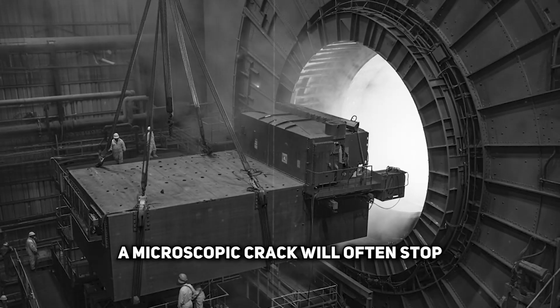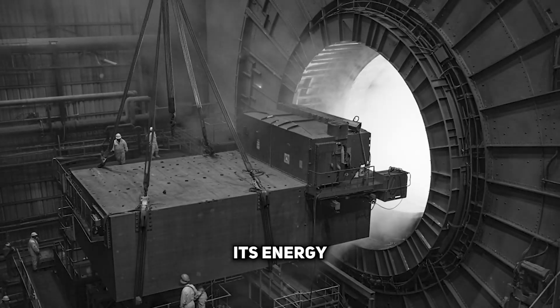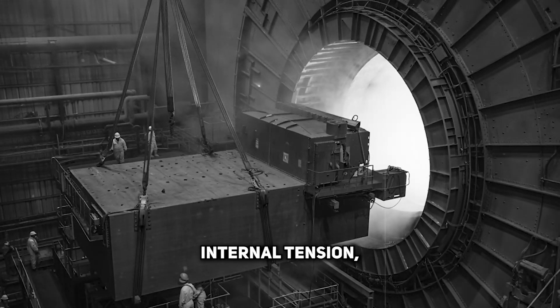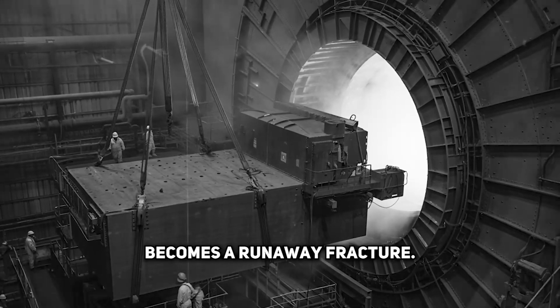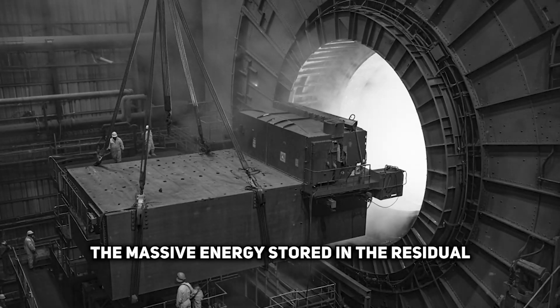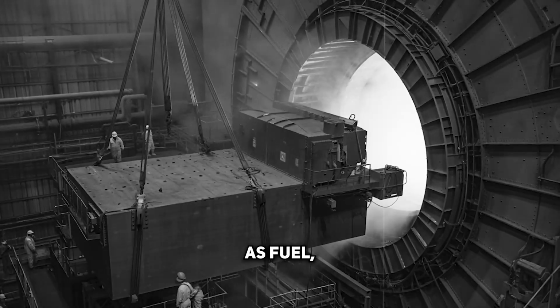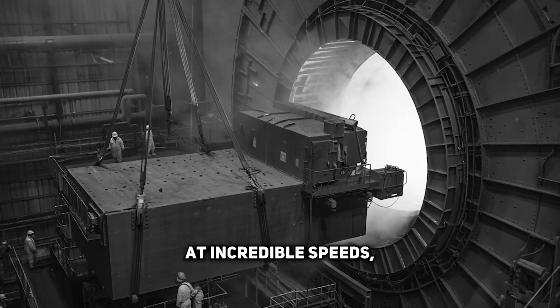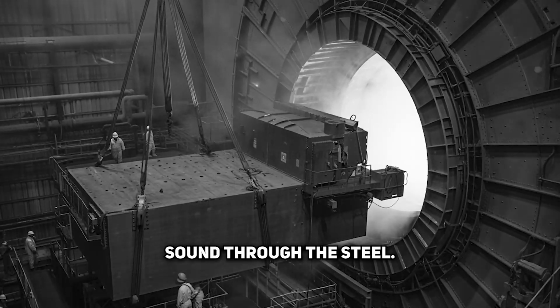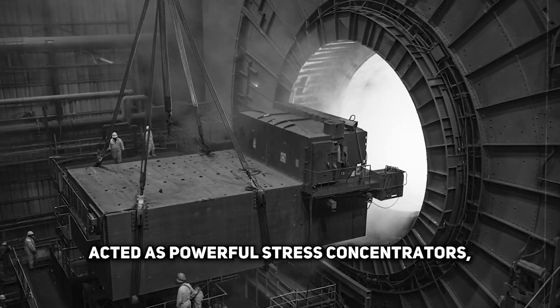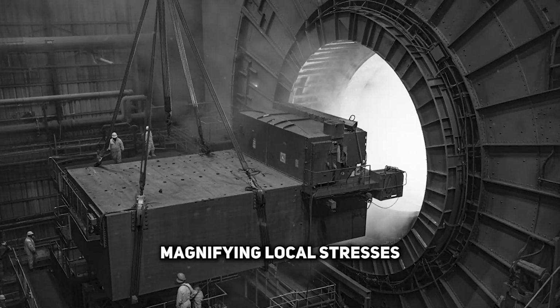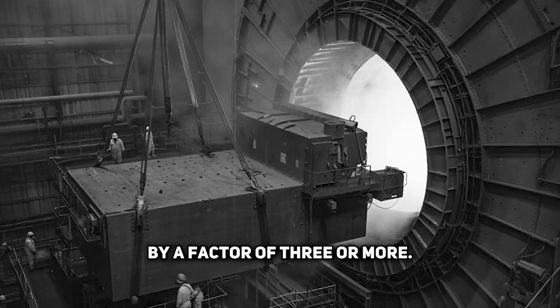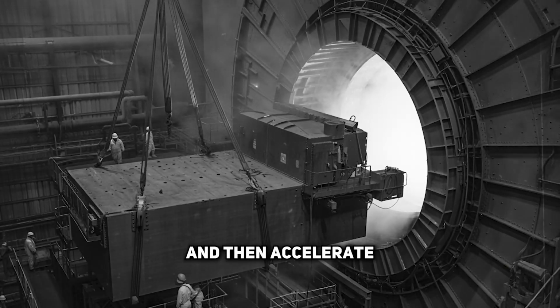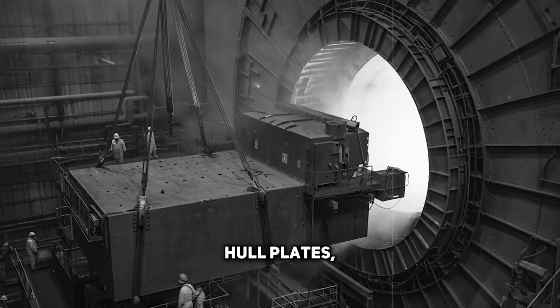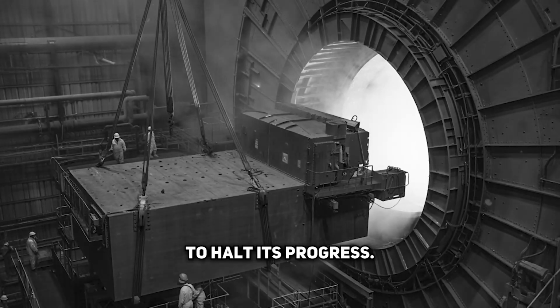In ductile steel, a microscopic crack will often stop, its energy absorbed by the material's ability to yield. In brittle steel that is already under high internal tension, that same microscopic crack becomes a runaway fracture. The massive energy stored in the residual welding stresses acts as fuel, driving the crack forward at incredible speeds, sometimes approaching the speed of sound through the steel. The sharp corners in the Liberty ship's design acted as powerful stress concentrators, magnifying local stresses by a factor of 3 or more. The crack would initiate at one of these points and then accelerate unimpeded through the continuously welded hull plates, encountering no natural barriers to halt its progress.